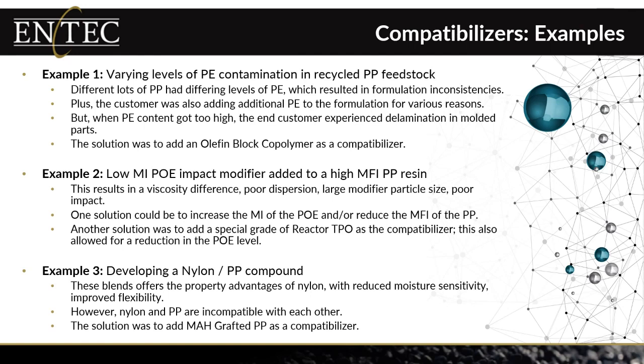Another good example is customers often use low melt flow polyolefin elastomers for impact modifiers. They work very, very well in polypropylene. And we like to use the low melt index materials to get the benefit of that impact modifier's molecular weight, which also helps improve impact, especially at cold temperature. However, if you get above a certain level of melt index in polypropylene, typically when you're above about a 30 melt flow polypropylene, if you recall, I mentioned that if you have too great a viscosity difference, you get more instabilities. And this is what happens as they go to higher and higher melt flow polypropylene, as your customers are demanding these higher melt flows. Using these low melt index POE elastomers causes a problem. You get poor stability, you get poor dispersion, and you end up with poor impact.